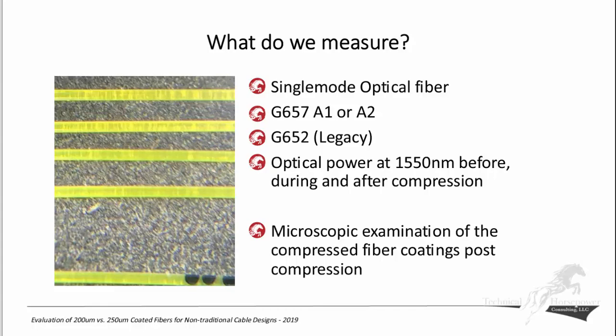Now, anyone who knows me knows that I never throw fiber away. So I actually had a spool of one of the major suppliers' fiber from about 10, 11 years ago, which had a previous coating system on it. And it was a G652 fiber, and I held on to that and used it as a reference fiber, if you will, as a control for the experiment. And what we looked at was we measured the optical power at 1550 before, during, and after compression. We also examined the compressed fiber coatings post-compression.